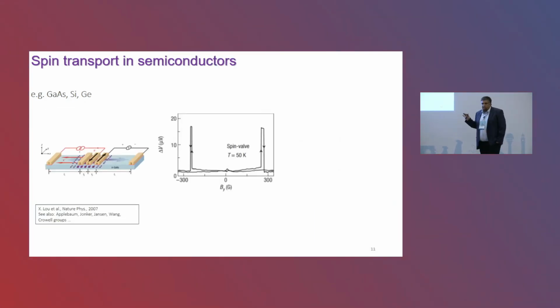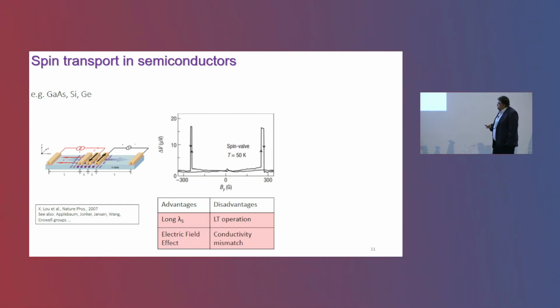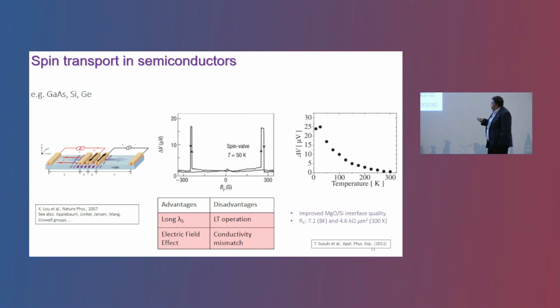Spin transport in semiconductors was also studied very extensively, especially with silicon, gallium arsenide, and germanium. The results were quite promising. They work excellently at low temperatures, but whenever you went above 80 Kelvin, the spin transport generally died in these materials. But recently there is another group showing that in silicon you can still get room temperature spin transport by, again, improving the contact resistance.